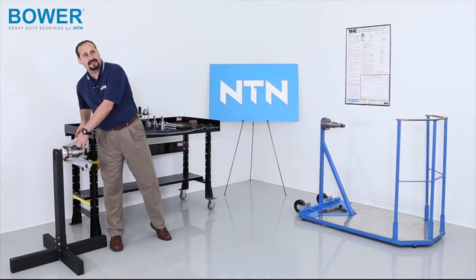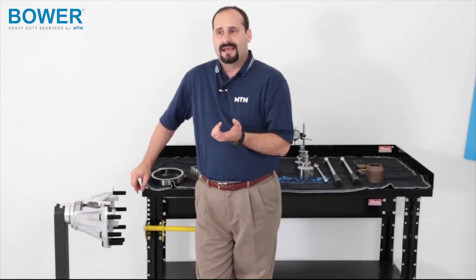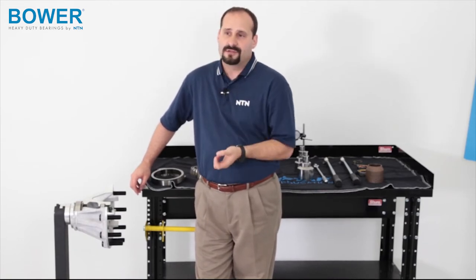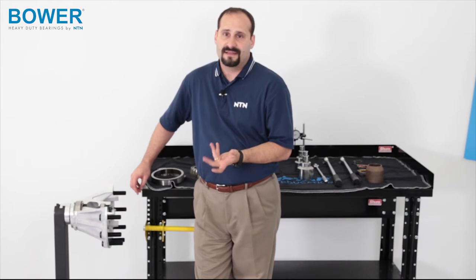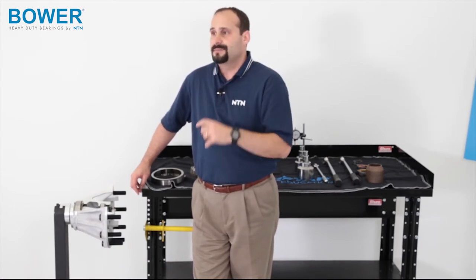The rib flange, when you cycle load on that rib flange, a case carburized part can last for roughly 100,000 cycles. Through-hardened parts from overseas suppliers that we've tested have lasted for roughly only 10,000 cycles. So, 10 times longer life.